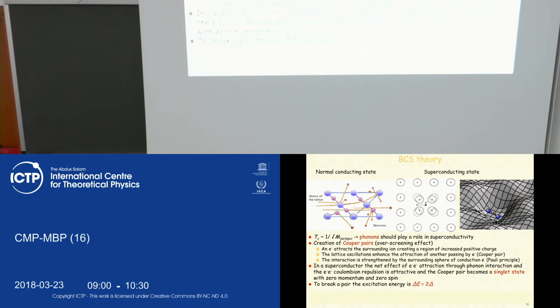So to say it again, phonons create an attractive potential for two electrons, and as a result, the Cooper pairs are formed. We discussed that the typical size of the Cooper pair is associated with a gap. The spectrum of elementary excitations of superconductors is gapped, and this gap actually controls the size of the Cooper pairs. And according to the gap taken from experiments on specific heat or tunnel current experiments, with a tunnel junction between normal metal and superconductor, this gap is of the order of a few kelvins, which means that the size of the Cooper pair, which is inversely proportional to the gap, is quite big.